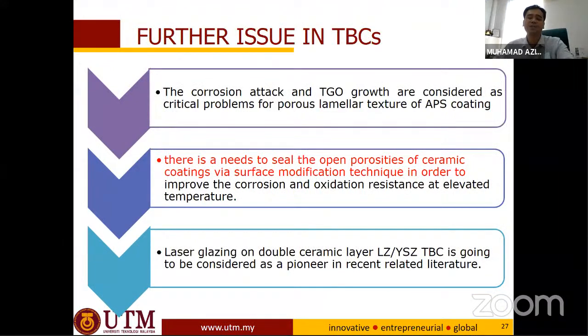Right. However, this research of ours is good, but it does not stop there, because issues in TBC continuously happen. For example, corrosion attack and TGO growth are considered critical problems for the porous lamellar texture of APS. APS stands for atmospheric plasma spray coatings, the normal method widely used in industry. But this method provides a porous structure. Therefore, there is a need to seal the open porosity of ceramic, like YSZ just now.